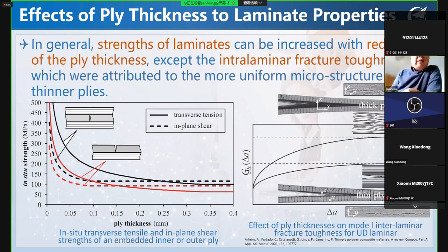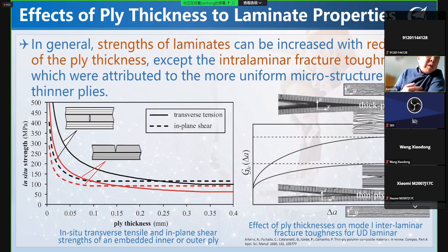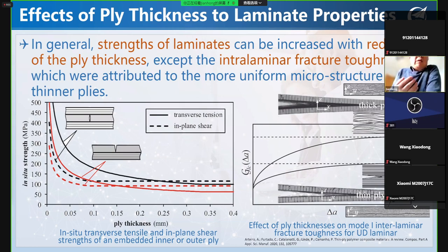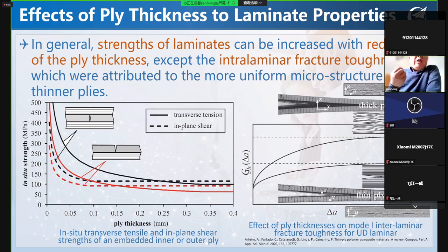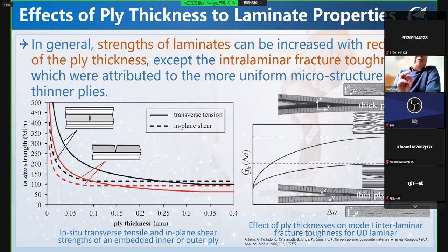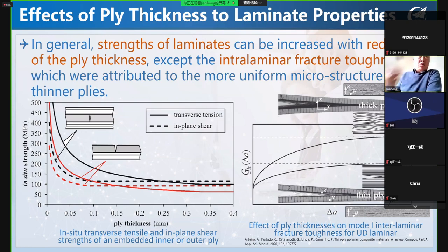These defects further link to structure features, tooling, and other manufacturing processes. So if we only focus on the material behavior itself, it will not solve the problem for design. Furthermore, the ply thickness of the laminate strongly affects the laminate behavior. When we reduce the ply thickness, the strength can be improved — this is called in-situ strength. But when ply thickness is reduced, although most strength behavior increases, the intralaminar fracture toughness will be reduced. So we need to carefully balance and select the ply thickness in the structure design to meet design requirements and minimize manufacturing time.